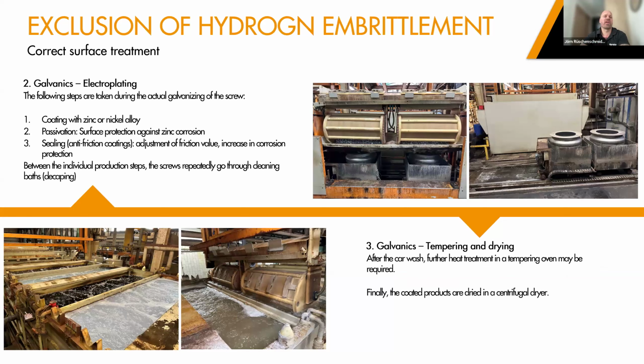The next step is the different types of electroplating. If you use a standard zinc, you have to keep your zinc substrate diffusion open, so that even hydrogen can diffuse out of the screw. The more layers you put, like special treatments, like clear coat treatments, the more you might trap the hydrogen in the screw. So just the standard zinc coating is the one that is least prone to HE, but still, what we do after the process with the zinc coating on there, which is diffusion open, as I explained, we still temper it one more time to be sure that the molecular grid is relaxed and that all the unwanted materials diffuse out of the screw.